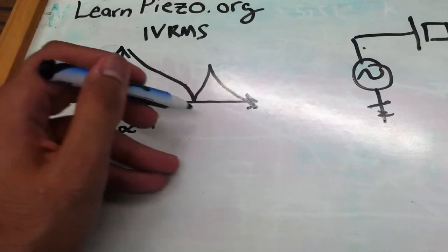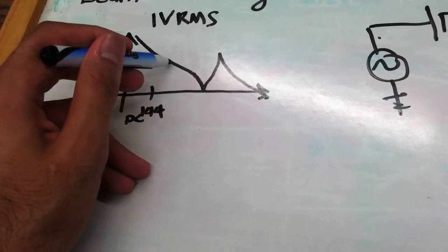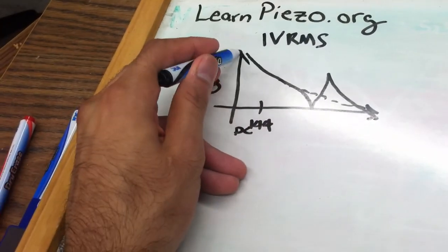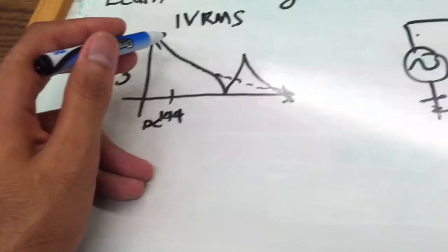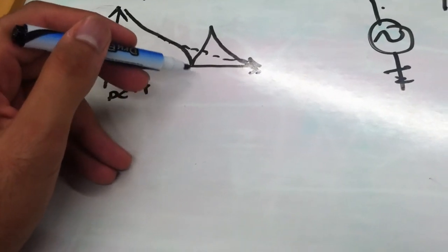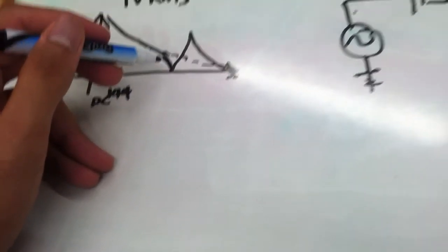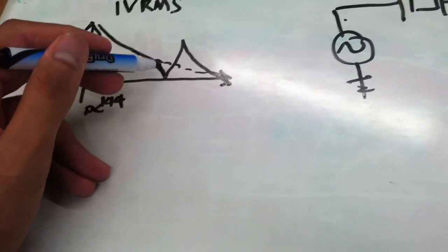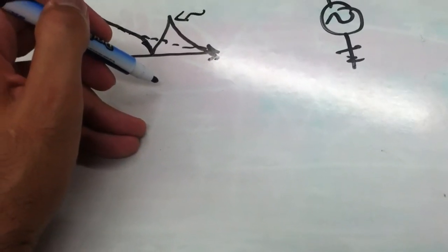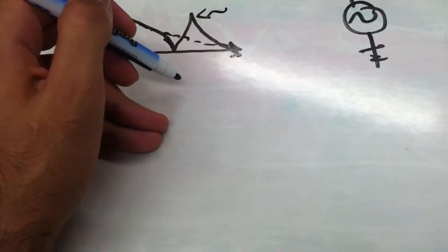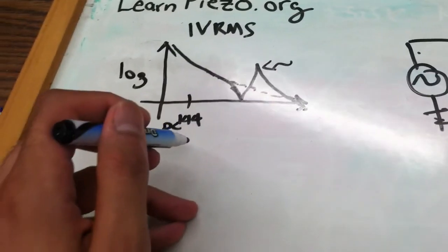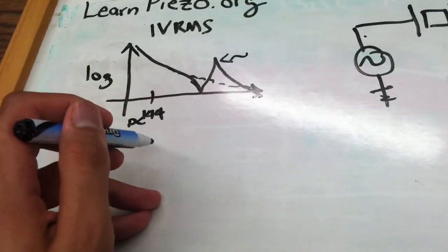So this is not zero again, basically we have two things happening here, or perhaps three things. We have the off-resonance case, where the piezoelectric material is acting like a capacitor, very clearly. And we have the resonance case, which results in a minimum impedance, and that is the mechanical resonance of the system. And here we have the anti-resonance of the system, which is a sort of coupling between the mechanical resonance and the electrical clamped response of the material.